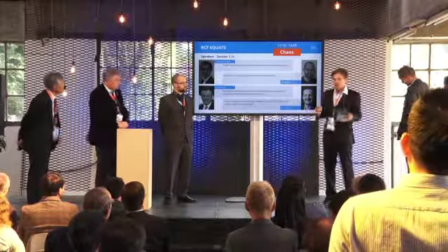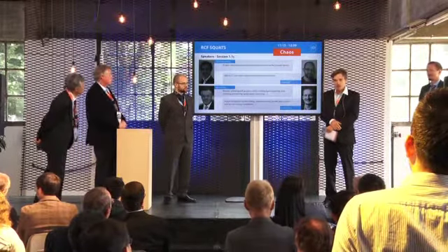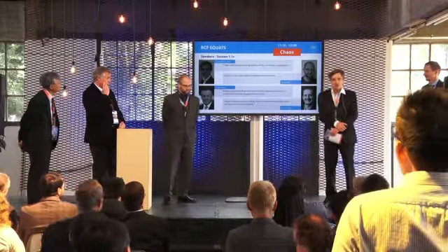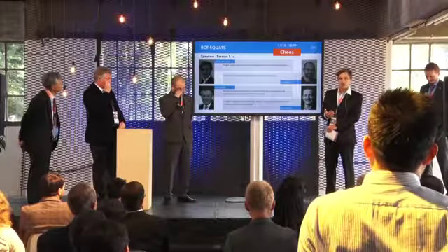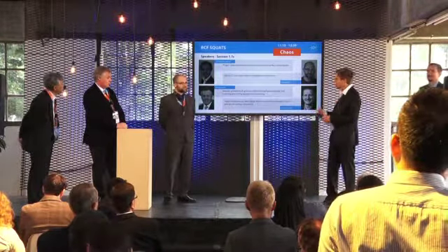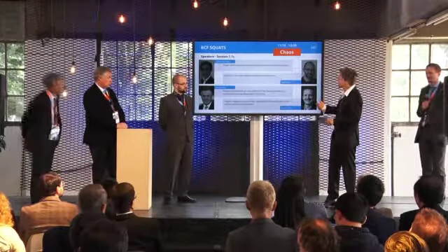geometrical deviations, initial geometrical deviations, are just an example for some local anomalies which can lead to local variations of the contact conditions. And these local contact conditions can continue and lead to some local behavior on the rail surface which may lead to squats.